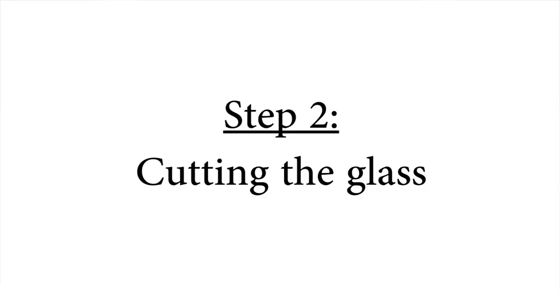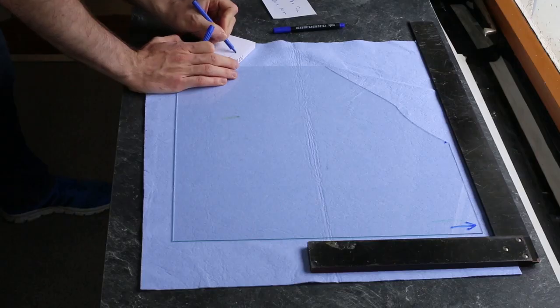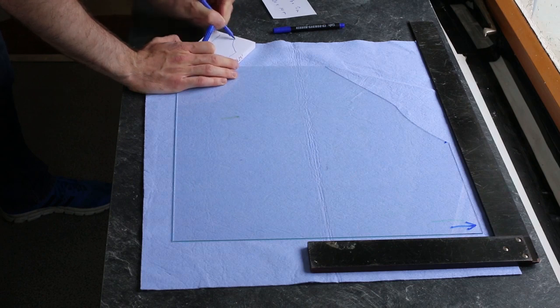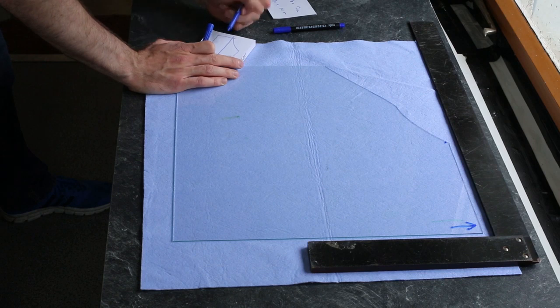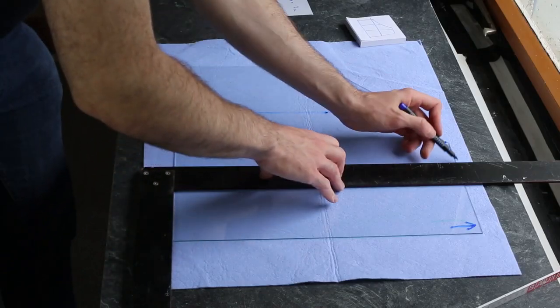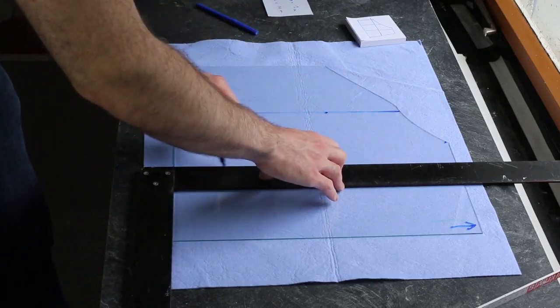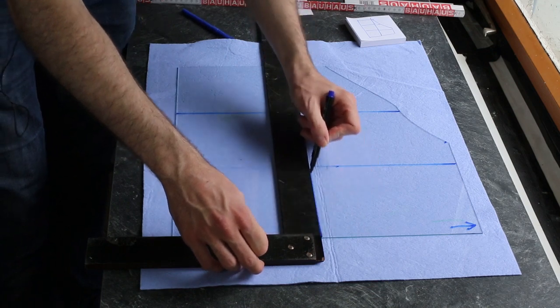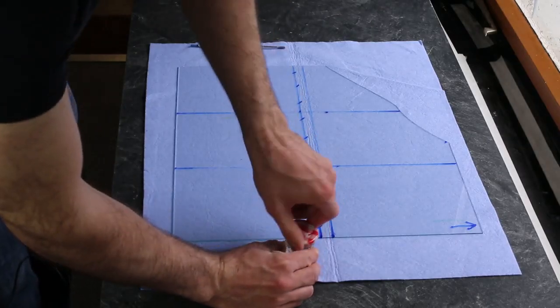Step 2. Cutting the glass. I use standard float glass for making holograms. Optical grade glass doesn't yield better results. First, I draw a sketch of how I want to cut the glass. As you can see, there is an arrow on the glass indicating the direction of the parallel lines pattern that I checked for under green laser light. I will cut my plates a little taller than wide. That's how I can remember how the pattern is oriented. In this case, I'm cutting plates sized 21 centimeters by 14 centimeters. The glass thickness is 2 millimeters.